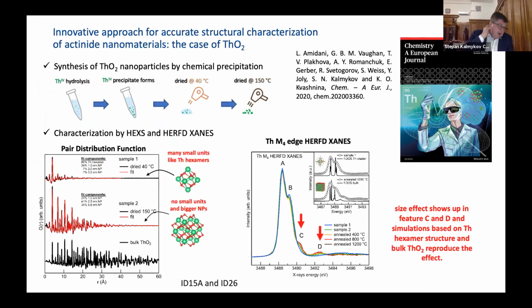Again, I would like to show a very powerful technique, the pair distribution function, PDF, that can give us the long range order in nanoparticles and in some hexamers that we see. So how was the experiment done? We took a thorium-4 sample, then we increased the pH. We have the hydrolysis, and before the particles are precipitated, we have some polynuclear species that are probably hexamers.